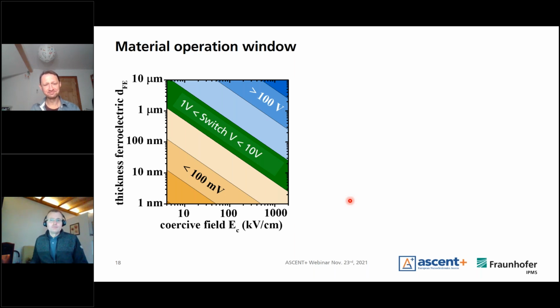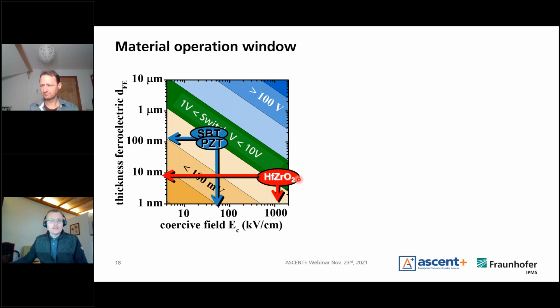In order to motivate the use of ferroelectric hafnium oxide, it's worth looking at the operation window. If we take, for instance, perovskite materials, which have also been implemented in applications so far, we are in the range of a thickness of 100 nanometers in order to be in a reasonable switching area. And if we implement hafnium zirconium oxide, for instance, we have much higher coercive fields, and that allows us to go to much lower thicknesses with the material.